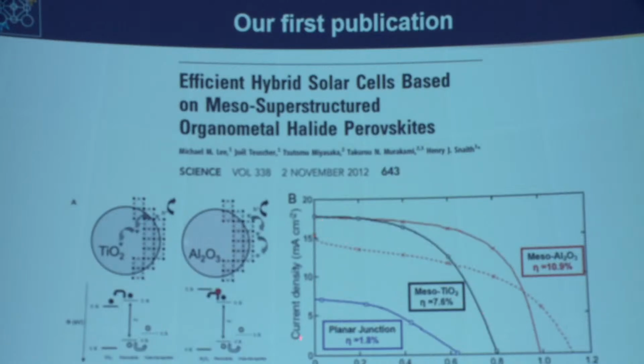What I'm showing here is current voltage curves, current density against voltage. It's how we measure a solar cell, where power is obviously the product of current times voltage. The red curve, the alumina, pushes out to higher power, current times voltage, than the one on TiO2.